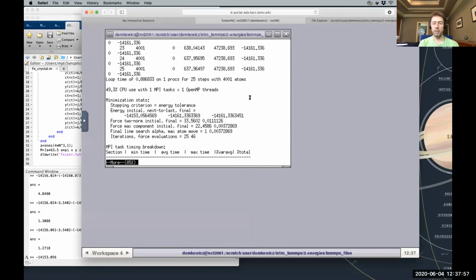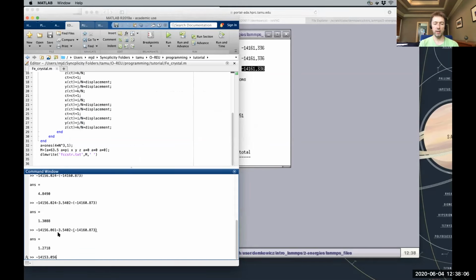All right. And now I go all the way back down to the bottom. This is the final energy. So if I want to know how much the energy dropped, I take final minus initial. So I'm just going to write in the final energy here. Final energy is minus 14,161.336 minus the initial energy, which is this negative number. Okay. So as a result of this relaxation, my energy decreased by 8.28 electron volts. Is that a lot?